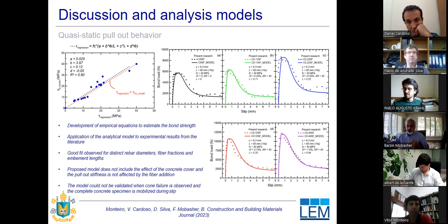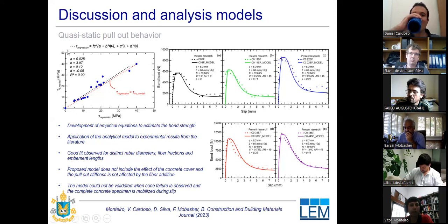So based on the results from the literature and from this experimental campaign, we could also make an empirical equation to evaluate the maximum bond strength for the rebar in the FRC matrix and try to correlate empirically the maximum bond strength based on those material and geometrical parameters.